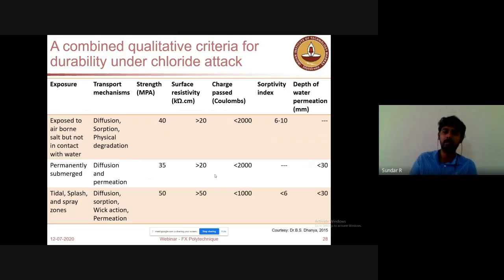service life. So when you need a particular service life, and if you decide to have a 50-year service life in a tidal zone, you should always have a surface resistivity greater than 50 kilo ohm centimeter. This has been put forward to the codal committees and all. So now our next revision of IS 456 will have some of these numbers.